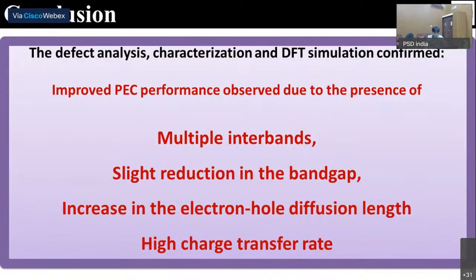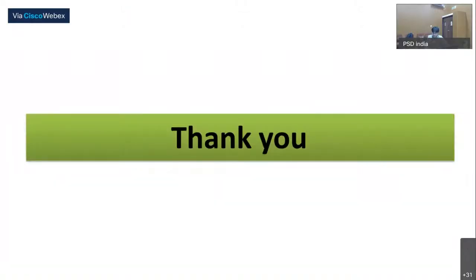So with this I will conclude the presentation. By defect analysis, characterization and DFT simulation, we confirm that especially for the sodium doped bismuth vanadate system, we see the improved PEC performance for water splitting and hydrogen generation due to formation of multiple interbands. There is a slight reduction in the band gap, and an increase in electron hole diffusion length. That means we reach up to a maximum of 91% bulk charge separation efficiency and high charge transfer rate. Thank you.